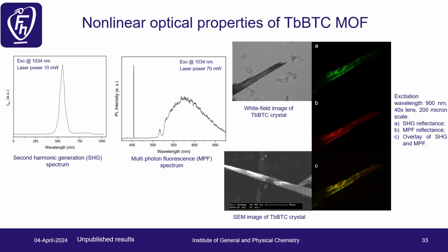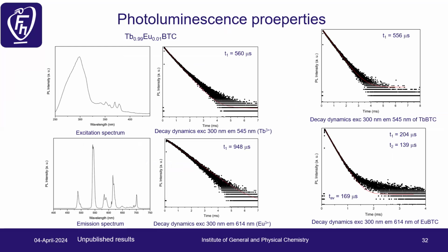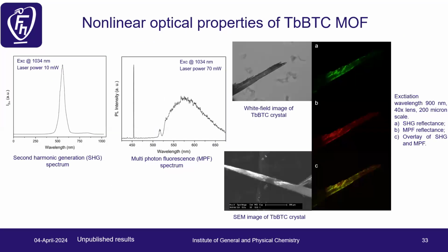So what we can see is the ligand excitation. In this case we don't see it, but with higher concentration we see a little bump around 450. At the end we also did some microscopy where we used a 900 nanometer wavelength as excitation, and you can see second harmonic and multiphoton nicely, and we can see that they are different when we overlay the images of second harmonic generation and multiphoton.